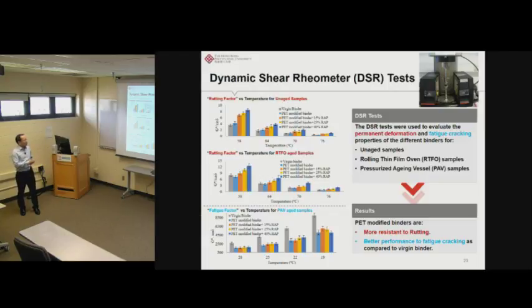So from this test, we noted that after adding the PET additive, which is the second one, compared with the first one, in most cases it slightly increased the rutting factor, but not that significantly.